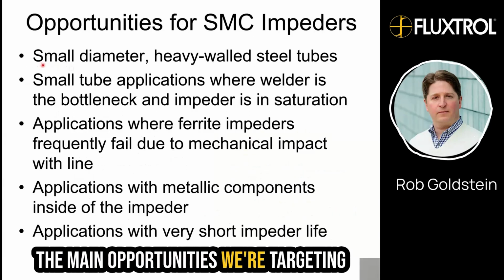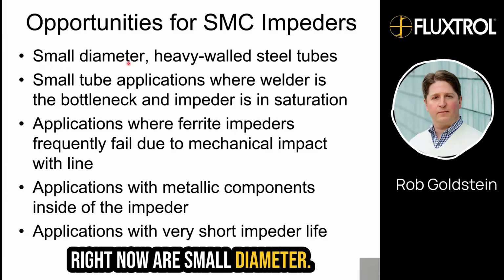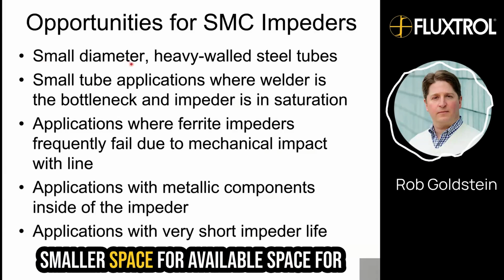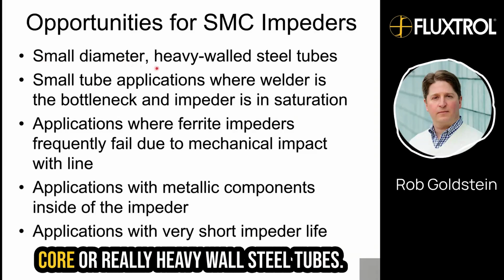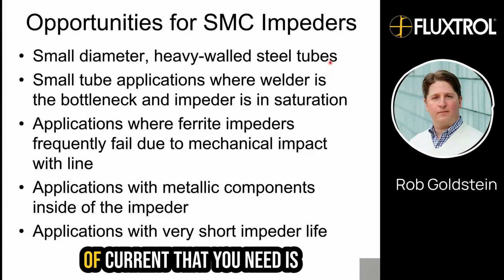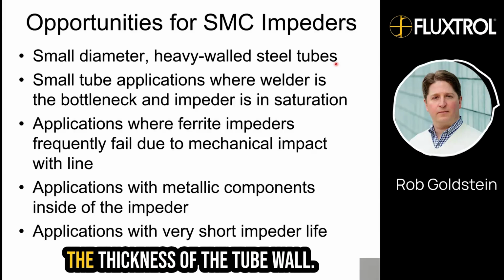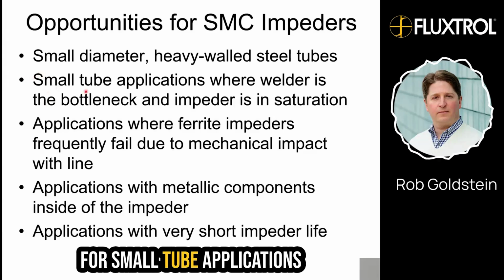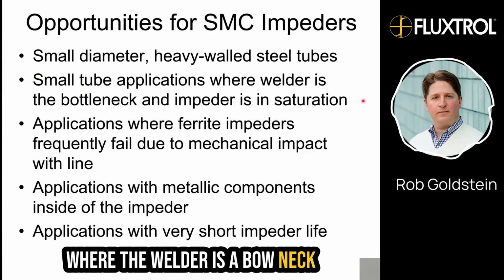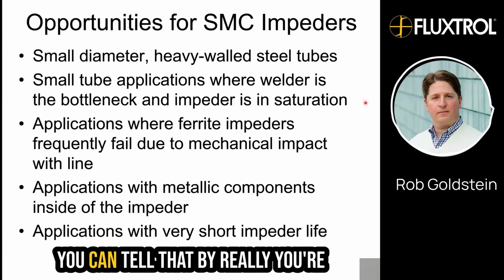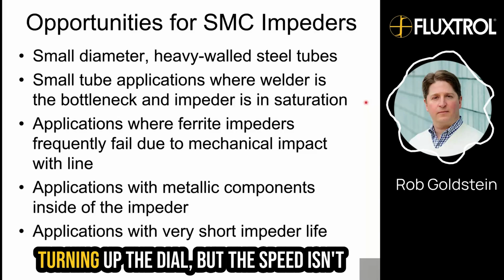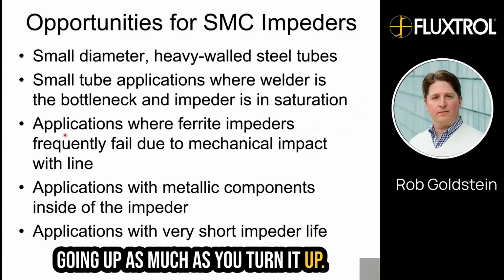The main opportunities we're targeting right now are small diameter. That means you've generally got smaller available space for core, or really heavy-walled steel tubes, because the amount of current that you need is essentially proportional to the thickness of the tube wall. For small tube applications where the welder is a bottleneck and the impeder is in saturation, you can tell that by really, you're turning up the dial, but the speed isn't going up as much as you turn it up.